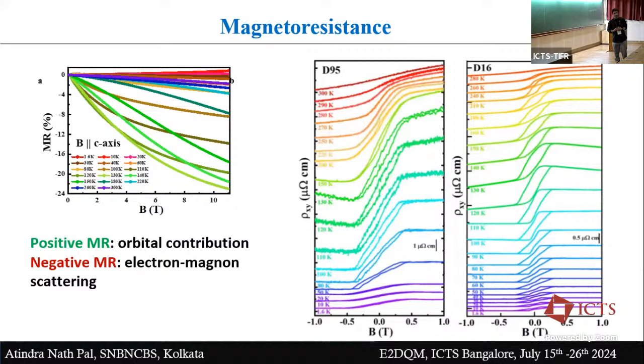Of course, there could be, because you see the spin reorientation. There could be a collinear phase, and there could be magnons which are coupled with the phonons, magnon-phonon coupling. This can also give rise to new phases, and this 50 Kelvin phase we don't know. So this is some kind of unusual phase, and this can give rise to really funny things.